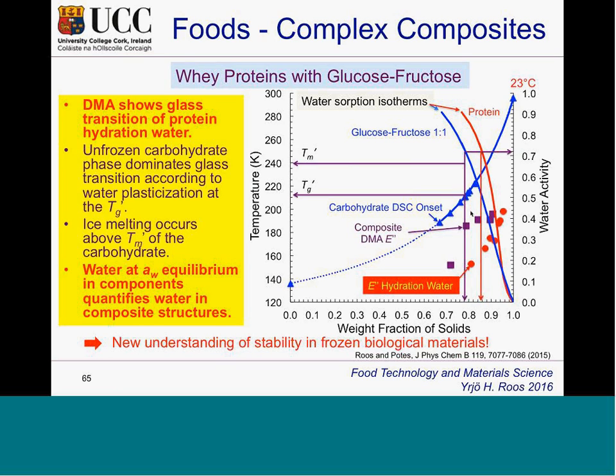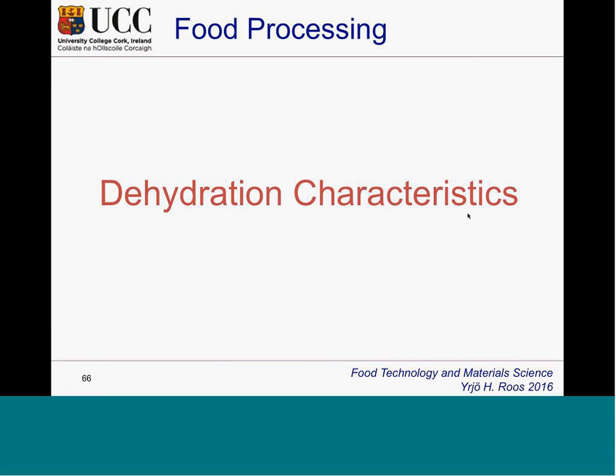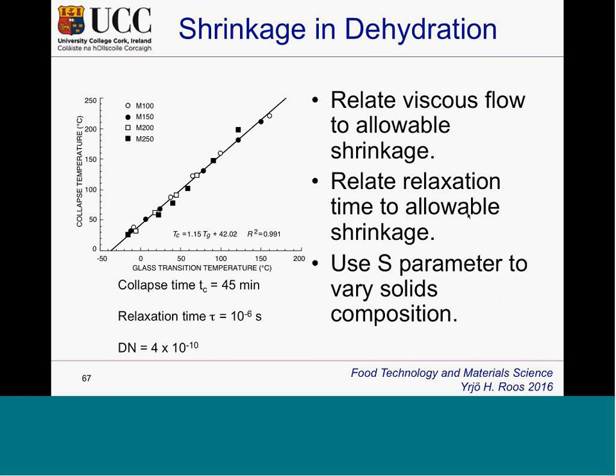Final words about dehydration characteristics. We have shown that the collapse temperature that I introduced earlier and the glass transition temperature are strongly related. So, very good correlation, and we could say that collapse time and relaxation time are related, and there's a fairly good number explaining that. So we just use the S parameter I introduced to characterize how it happens.